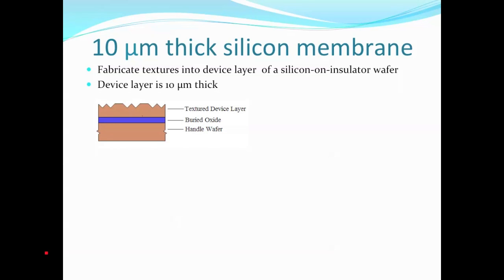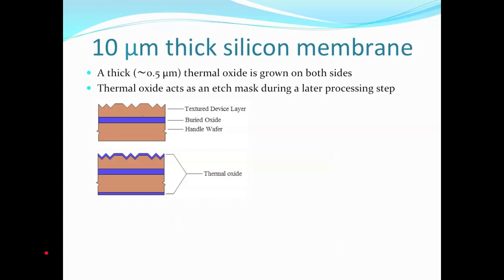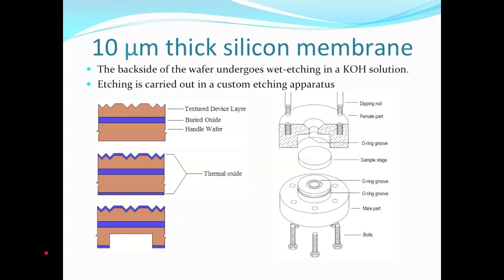We start with an SOI wafer, silicon on insulator. The device layer is 10 microns thick. Then we texture the surface using the process outlined previously. Then we grow a thick thermal oxide on both sides, which will act as a masking step in the later stage. Then, using a custom etching apparatus, we begin to etch through the handle wafer of the SOI wafer. We load the sample with the handle wafer upwards into this apparatus and dip it into a solution of KOH. KOH then attacks the handle wafer through the hole in the top there. Now this is where the thermal oxide comes in handy, because we found that we can't leave the membrane inside this apparatus for the whole etch.